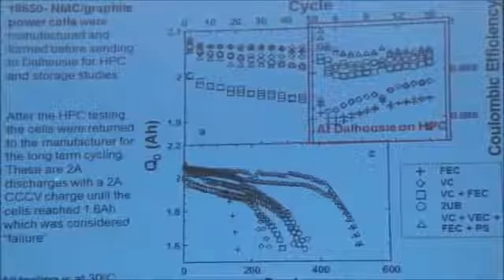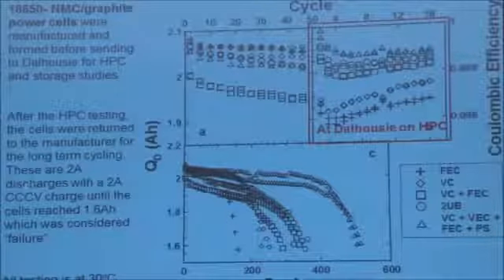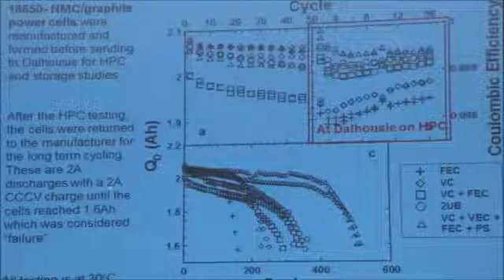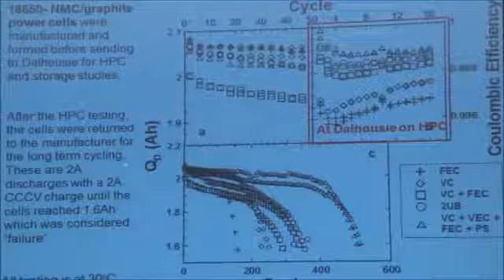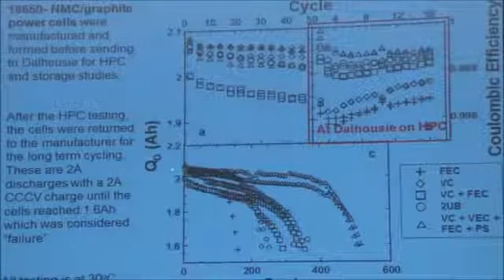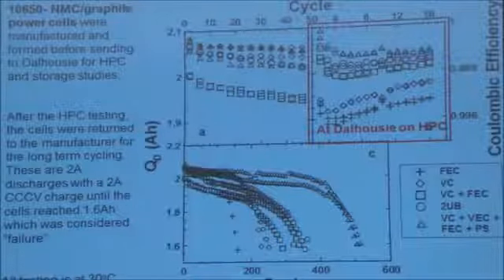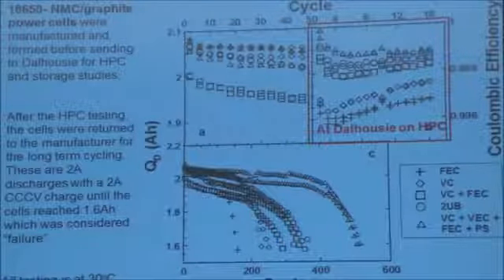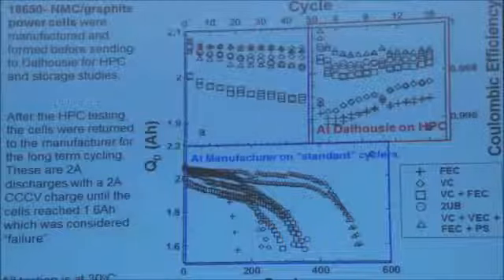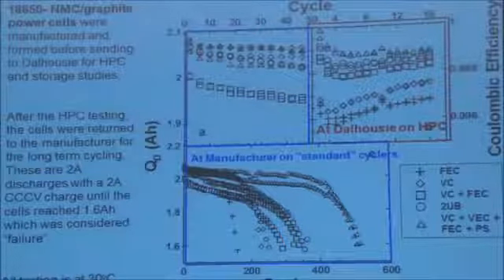We sent them back to the manufacturer for their long-term testing. And the long-term testing was done at 2 amp discharge and 2 amp constant current, constant voltage charge, so C rate for the battery people. And we continued the testing until the cells reached 1.6 amp hours. So in the blue boxes is where the testing was done at the manufacturer.